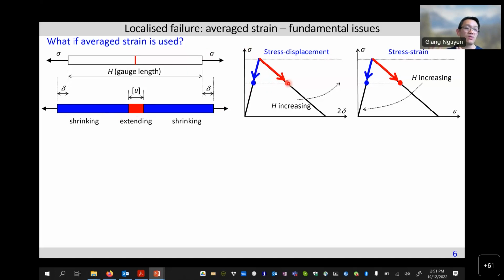Okay, so now we are an engineer. We need to work out strain. So what should we do? Basically, we divide the displacement here by the gauge length. We get this stress strain. But if we change the gauge length, what happens? If our gauge length is increasing, we get a different response. Okay, if it is increasing, that means we record deformation over a larger area, so it is softer in this case, and we end up having this. If this keeps increasing, we would get that behavior, and correspondingly, we get 3 different stress strain responses.